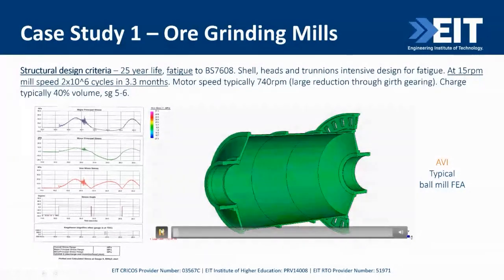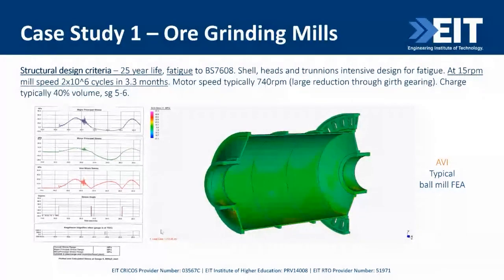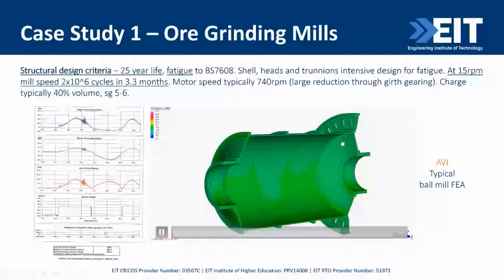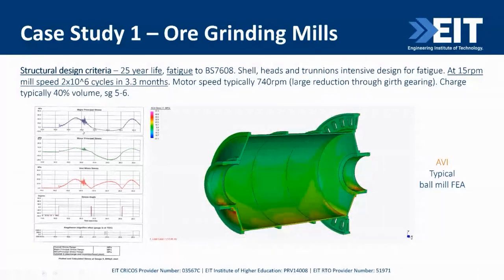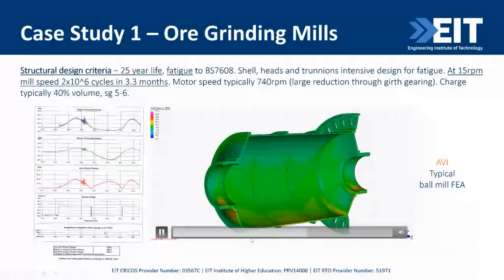So this is your typical mill in operation. This is obviously a half longitudinal plane of symmetry mesh, all solid elements, 15 RPM. And that video there is showing the major principal stress. So through every cycle, when you go from top dead center where you're in compression, to bottom dead center where you're in tension, we open up, and the tension to compression difference there is the stress range as per the strain gauges and the stress derivations. So, you know, that mill's 40, 50 mil shell thickness and massive trunnions and heads, there's still a huge fatigue problem because of this rotation and the charge loading as they rotate through the charge and through gravity.